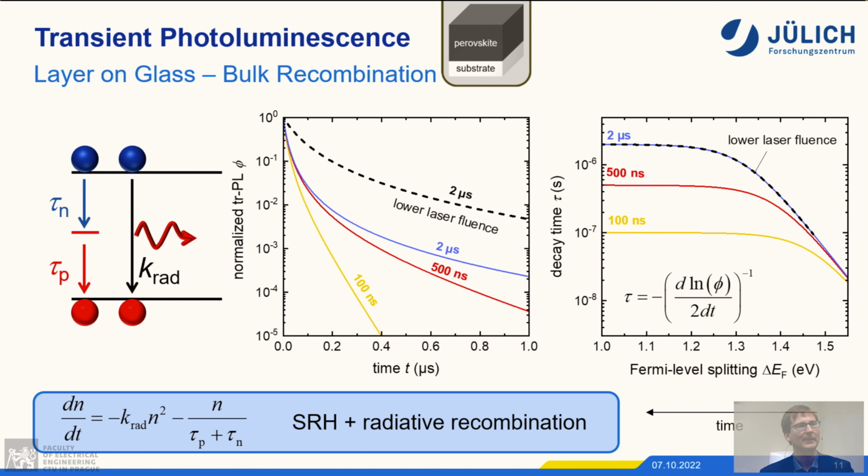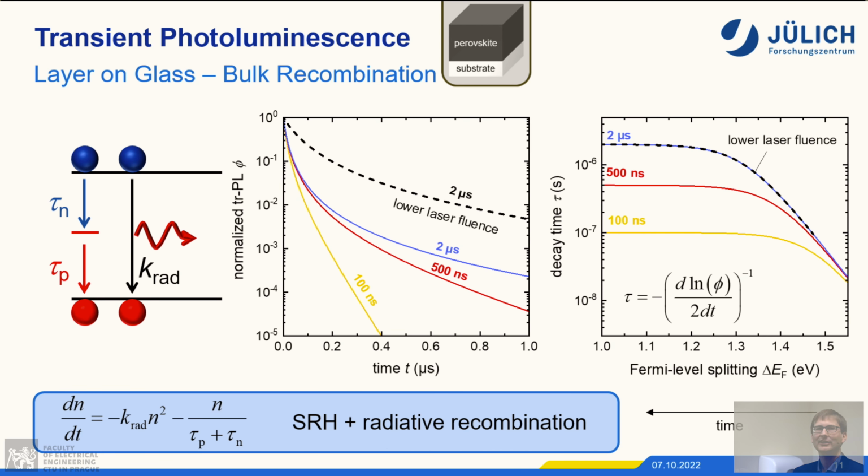But second, it's also affecting the carrier density that you have, and thereby the time dependence of your photoluminescence. Yeah? The non-radiative recombination is not your observable, but you still see it because you see the carrier density going down from getting fewer photons out. Yeah? So this is what some people find very confusing at the beginning when they look at photoluminescence.